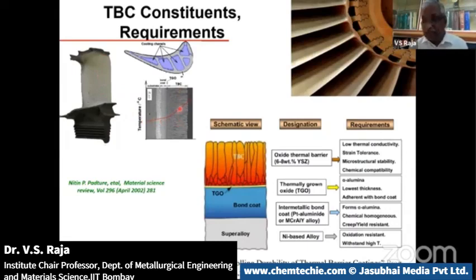There's a thermal mismatch between this metal and the oxide coating. In order to reduce the thermal strains, you have a bond coating, which has a coefficient of thermal expansion that lies between the oxide coating and the metal, and this gives you a nicely graded performance from the point of view of thermal expansion. Now, the point here is that when you cycle the temperatures, there is going to be strain involved in these coatings, which means the strain has to be tolerated.